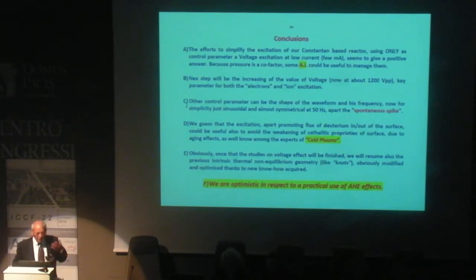Some possible explanations why we don't have decreasing of performance. One is the flux that we thought of at the beginning. Another is that in our regime we have a cold plasma. The cold plasma means the surface of the material is always catalytic. It doesn't die young forever. And then we think we have both effects. In the next step, we will use again a special geometry to increase the non-equilibrium condition. Putting all together, I finish. Maybe it will be the event when cold fusion will be practical, not too far from now. Thanks.